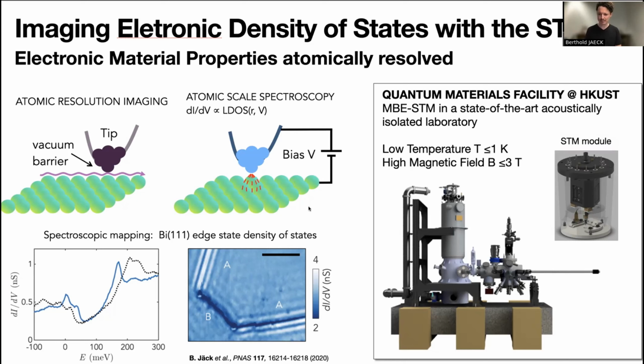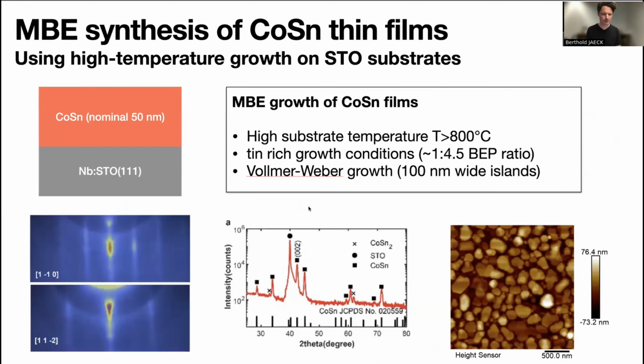Yeah, so this has been set up by my group about a year ago, and now you can see the results of our most recent work. For cobalt tin, it turns out MBE growth is quite challenging. This is mostly related to the chemistry of cobalt, which is a little bit more challenging than that of iron. So what we have been doing here is to grow a nominal film of 50 nanometers on top of, in this case, niobium-doped STO111. While the RHEED observation during growth looks somewhat nice, this can be quite misleading